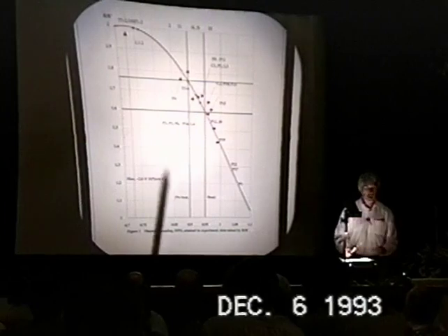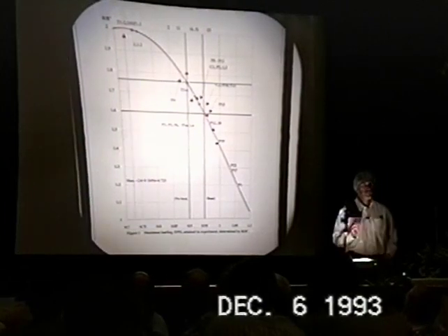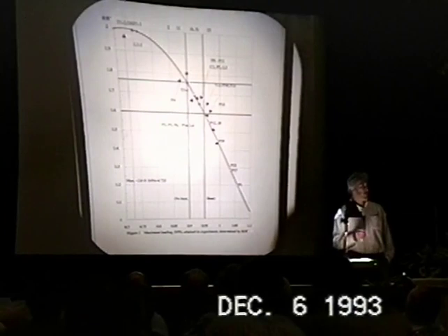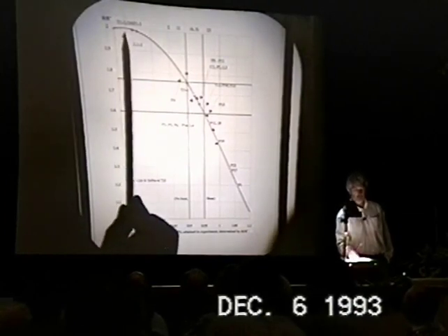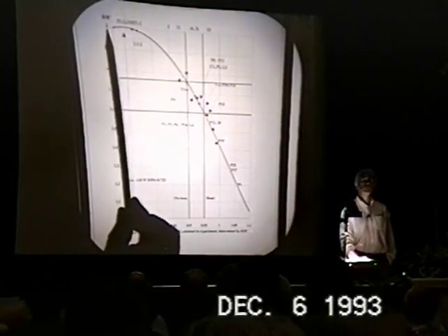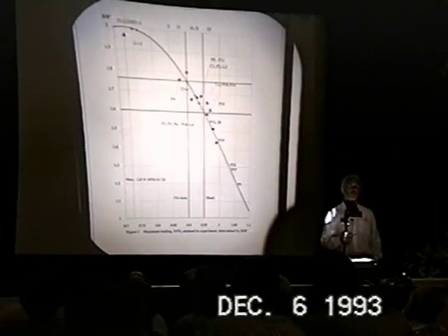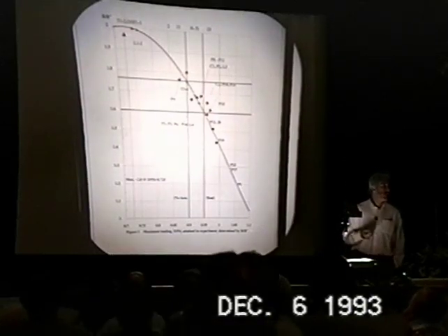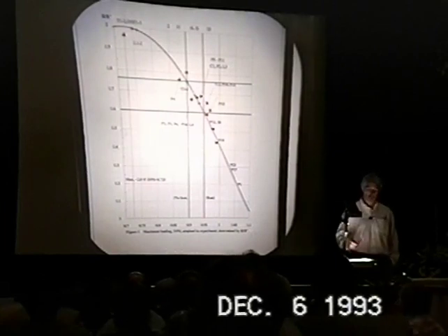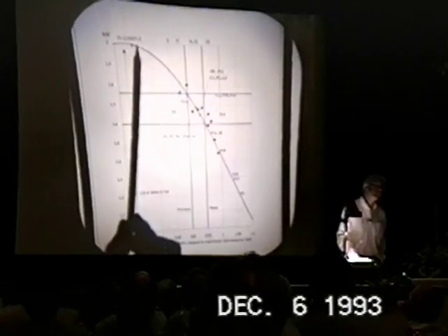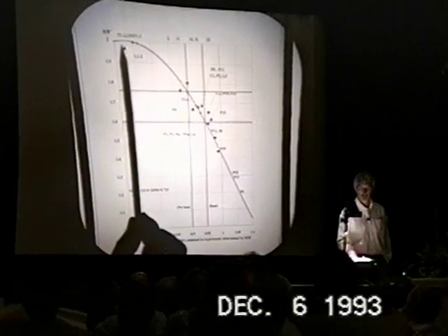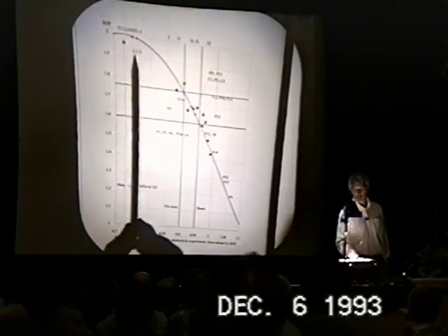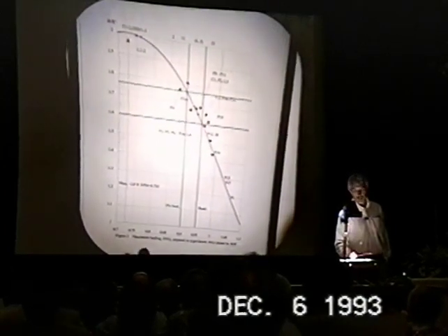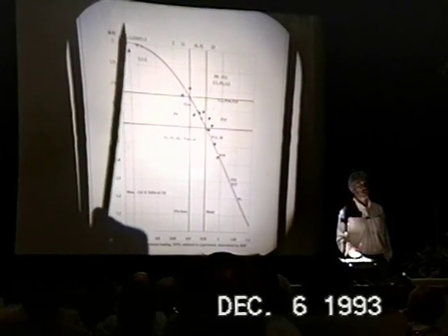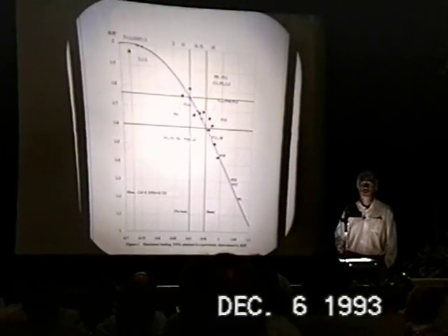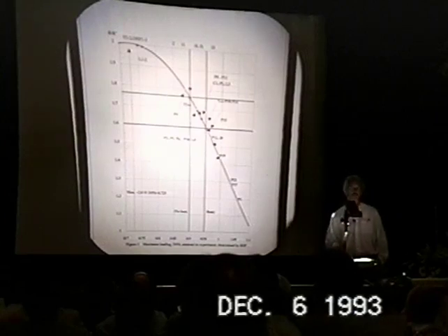Several things are salient about this. One is the electrode will never spontaneously deload much beyond this maximum. As long as you continue to evolve hydrogen on the surface of palladium, it sits there bathed in a 1 atmosphere hydrogen environment, and it will never spontaneously deload and go down the left-hand side of this hump. So, as a qualitative indication of loading, we can simply take the reduction of resistance as an indication of increased loading.